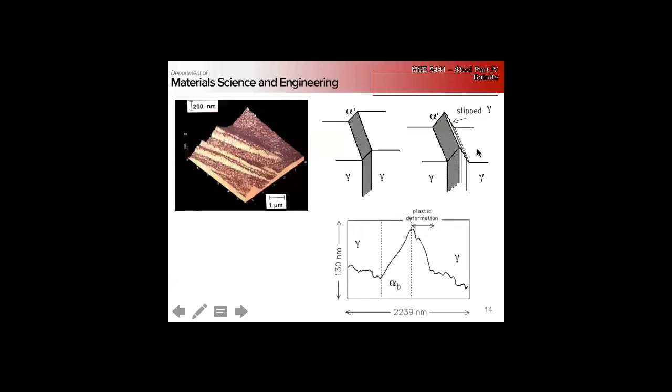These are very large strains, too large to be accommodated purely by elastic means. Whereas, remember, in Widmanstätten ferrite, you would have two variants with opposing shears grow next to each other to relieve that strain. With bainite, we get plasticity.